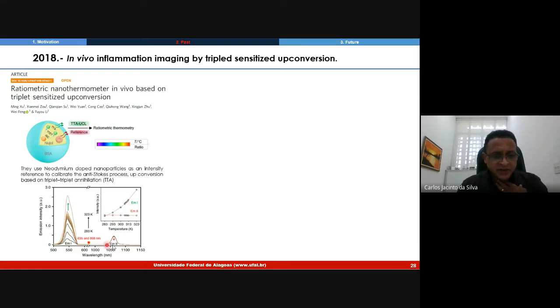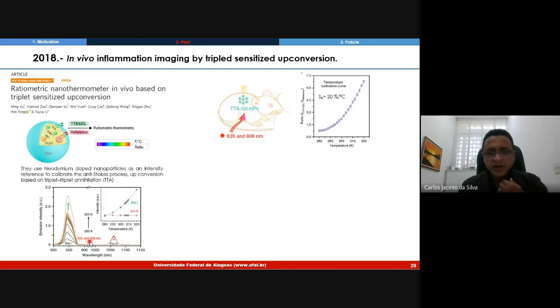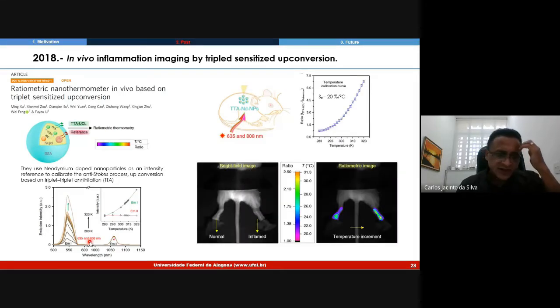Okay, in this case, using these two bands here. The problem of this system is the emission. The neodymium is the reference emission, and the triplet annihilation is another, very sensitive to temperature, emitting in the green. Is this the problem? Emitting the green outside of the biological windows.